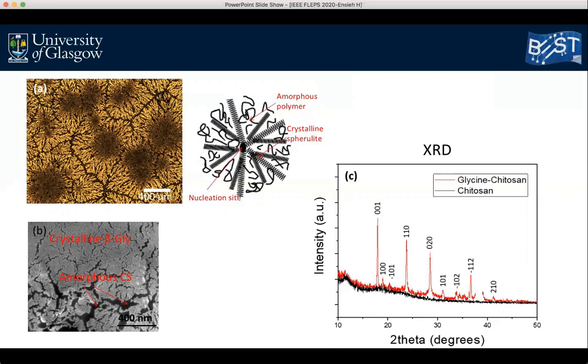So this result shows that chitosan effectively modulates the kinetics of self-assembly of glycine molecules into the crystalline structure, and the crystals were very stable inside chitosan. We made an XRD of the same sample after a few months, but it shows no change or phase transformation. And we think the stability of the crystal may come from embedding the crystal in the chitosan polymer, and also there is a possibility of electrostatic interaction between the molecular polar group of glycine and the functional group of chitosan.